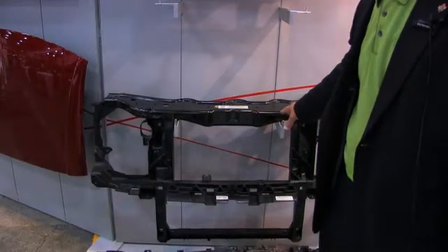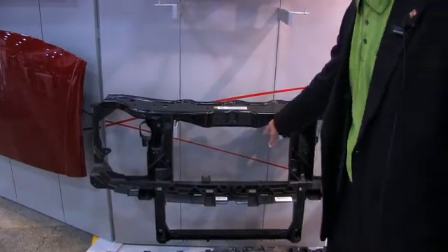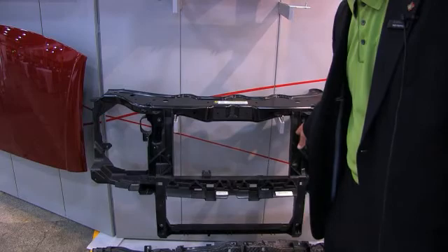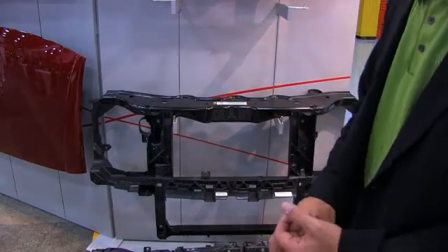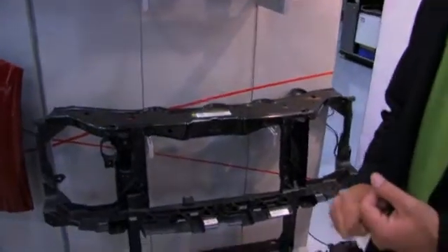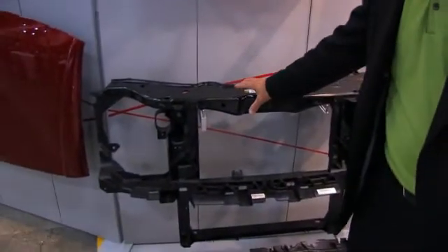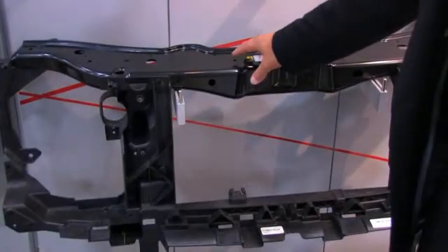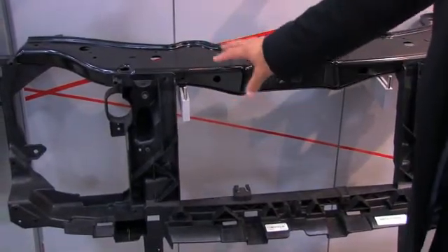This component is an example of a front-end structure that we produce using a long fibre thermoplastic that's directly compounded in our process here in Ontario — a 40% glass fibre reinforced polypropylene that's mated to a steel component that's stamped, e-coated, and then bonded to the polypropylene structure.